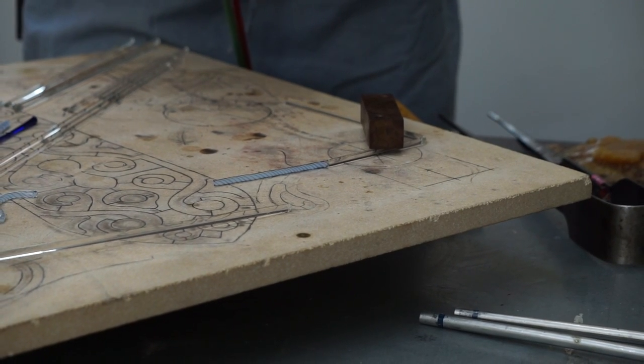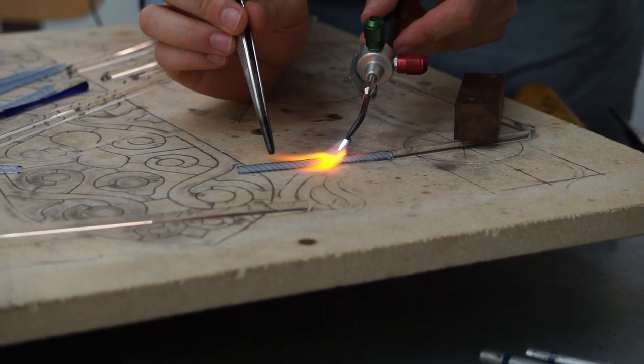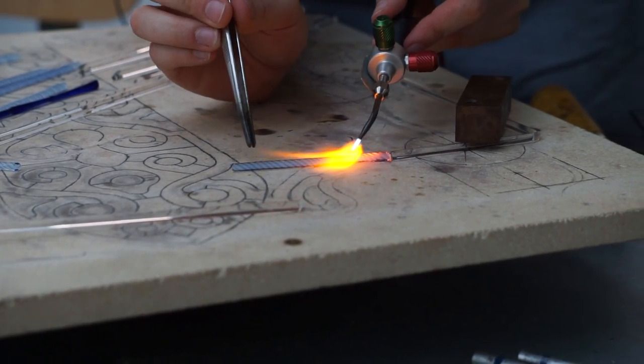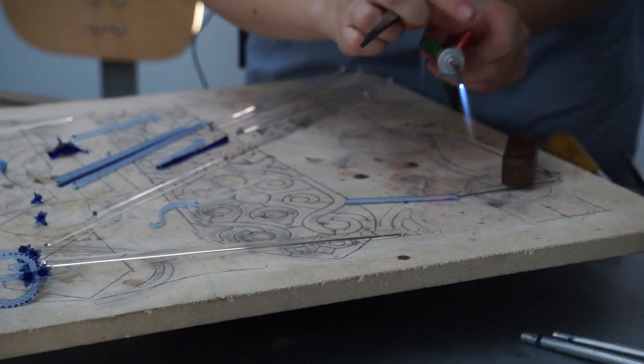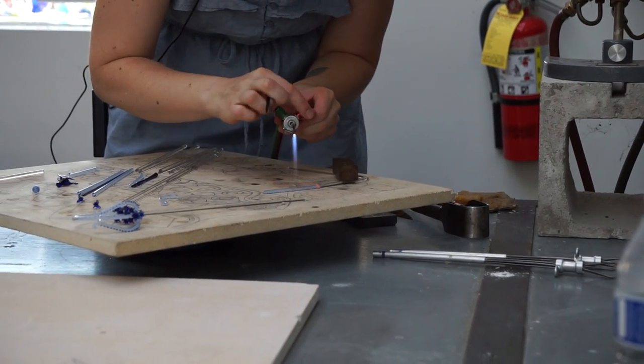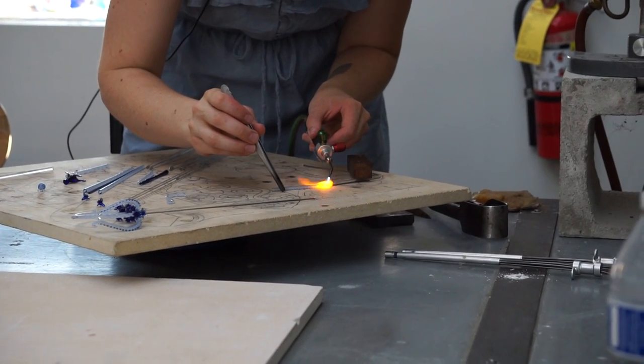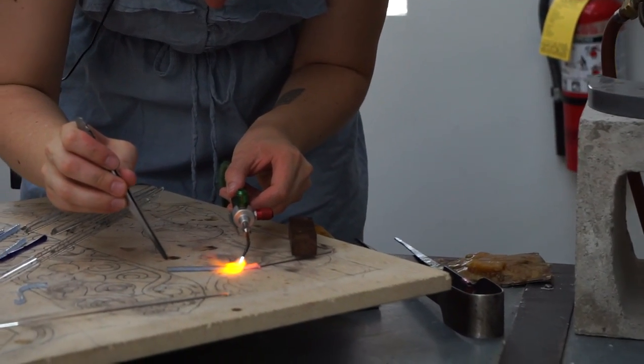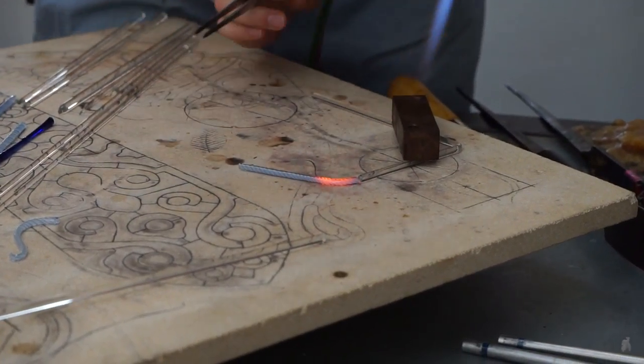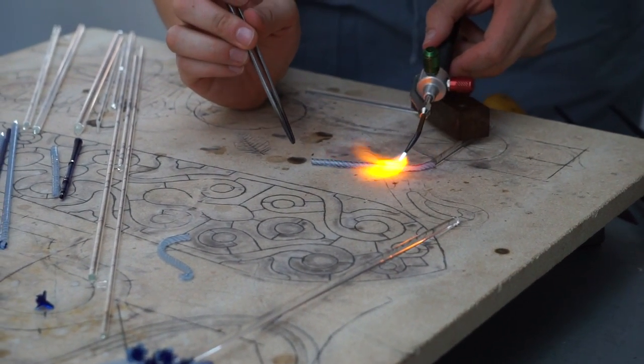I've got that stuck down. I'm gonna make a nice bushy flame and just sweep that over my piece of cane — very, very gently heating it. I don't want to heat it so much that it melts into a puddle. I'm heating a little and then bending, heating a little and bending. My cold seal was too cold and it came right off, so I stuck it back on. It's kind of fun to do with the twisty cane because the twist gets tighter wherever it gets bent and it looks really pretty.